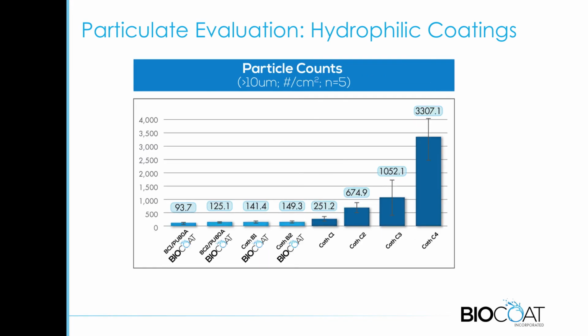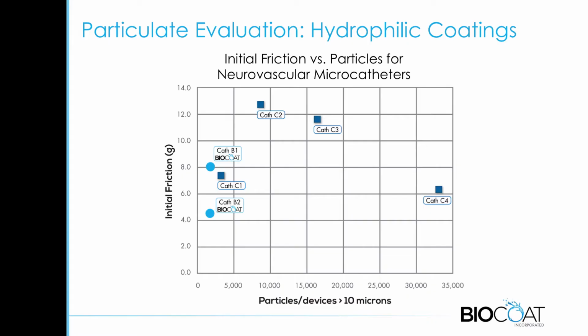So if you look also at the particle counts, we compare coatings done at Biocoat on tubing compared to devices that were coated at the manufacturer. You can see that our coatings actually are very consistent from ones coated here versus at our customer's manufacturing. These are shown in particles per centimeter squared to kind of normalize everything. But again, the numbers are remarkably comparable, and then the other devices are 10 or even 20x higher than some of these best-in-class devices.